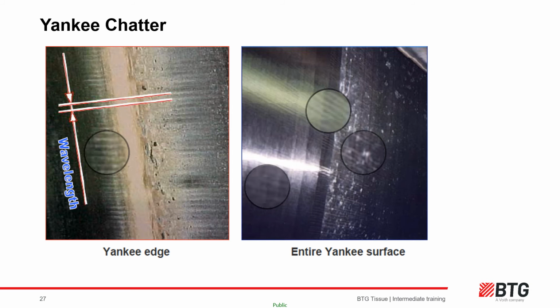Edge deposits and edge chatter are more commonplace than full width chatter. Edge contamination tends to happen from the overspray of coating or from jet capture from the headbox transferring from the felt to the Yankee, coupled with getting the edge relief correct on the blade holders. CD chatter marks will manifest themselves as coating coverage issues, both MD and CD, eventually leading to breaks, sheet defects, for example holes or chatter defined marks in the sheet. Once there, chatter will not improve of its own accord and will only get worse.